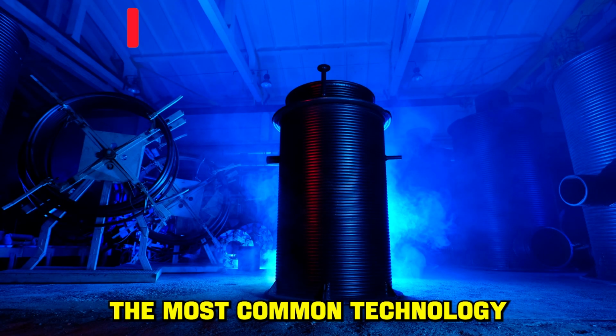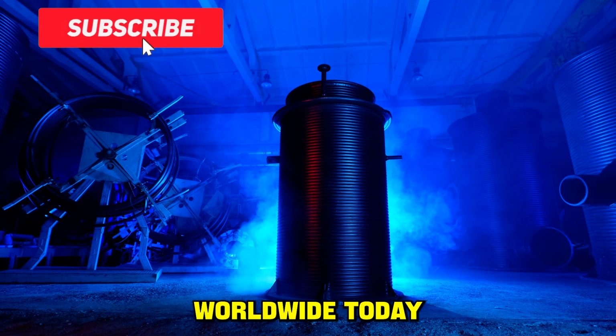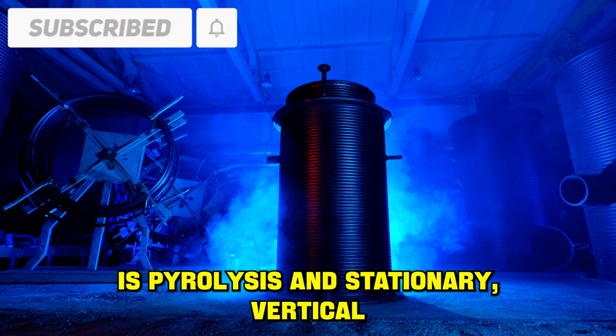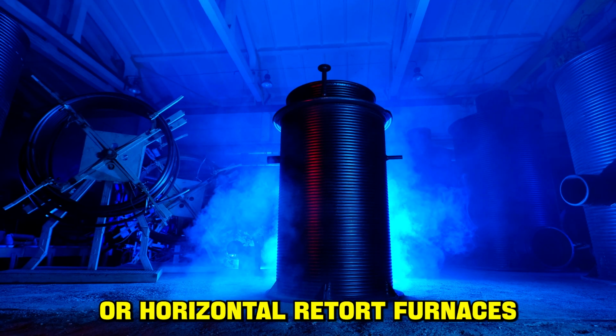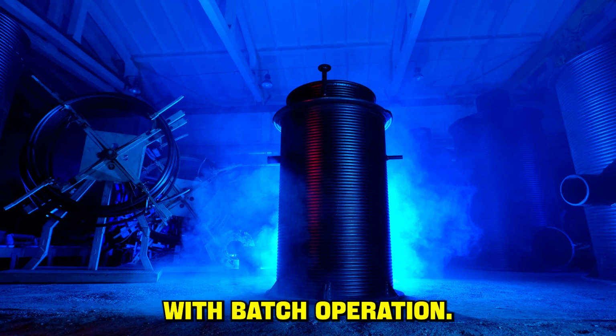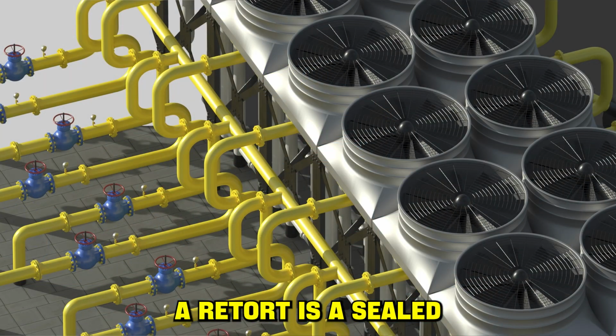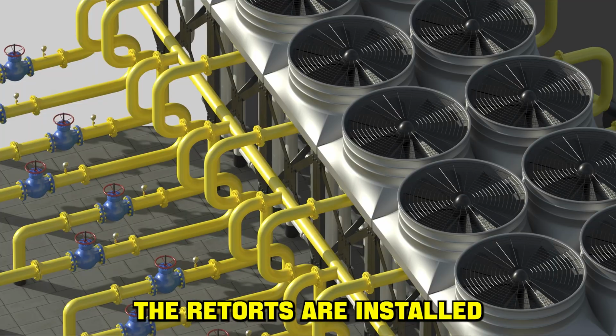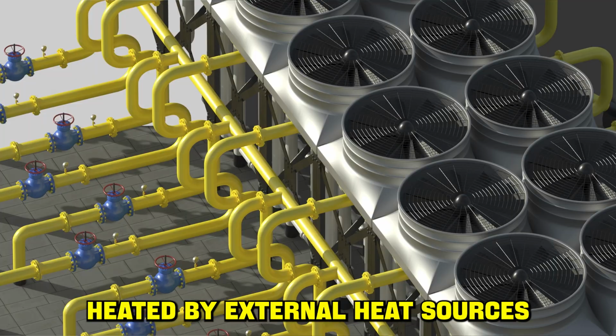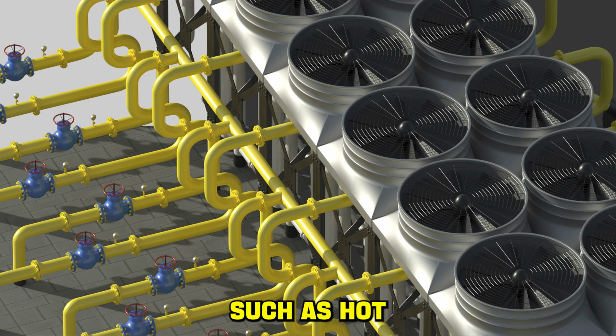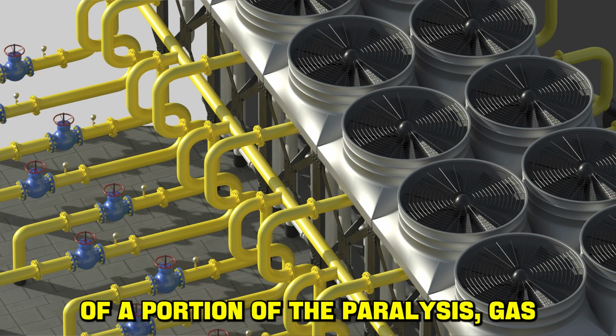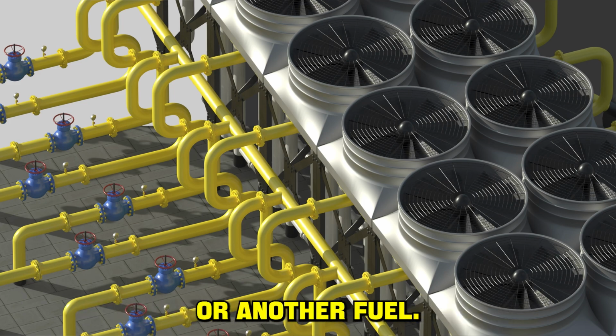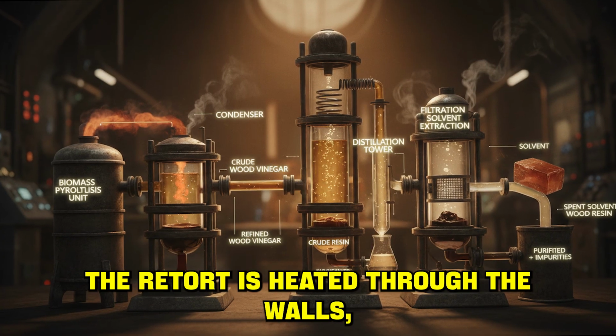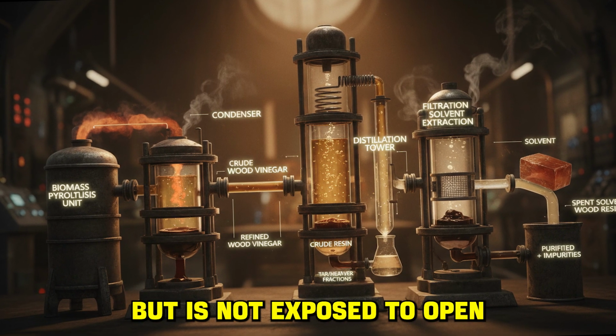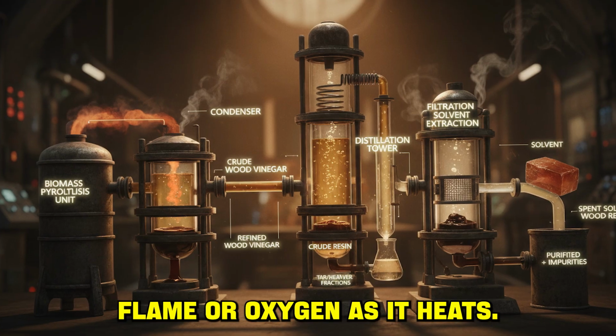The most common technology for producing high-quality charcoal worldwide today is pyrolysis in stationary vertical or horizontal retort furnaces with batch operation. A retort is a sealed metal or refractory chamber loaded with wood. The retorts are installed in a common furnace where they are heated by external heat sources, such as hot gases from the combustion of a portion of the pyrolysis gas or another fuel. The wood inside the retort is heated through the walls, but is not exposed to open flame or oxygen.